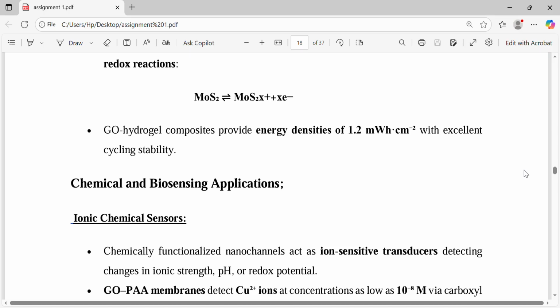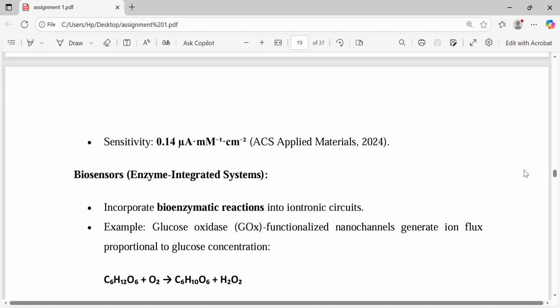Chemical and biosensing applications. Ionic chemical sensors: chemically functionalized nanochannels act as ion-sensitive transducers detecting changes in ion strength, pH, or redox potential. GO-PAA membranes detect Cu2+ ions at concentrations as low as 10^-8 molar through carboxyl group coordination. The response follows Nernst behavior.